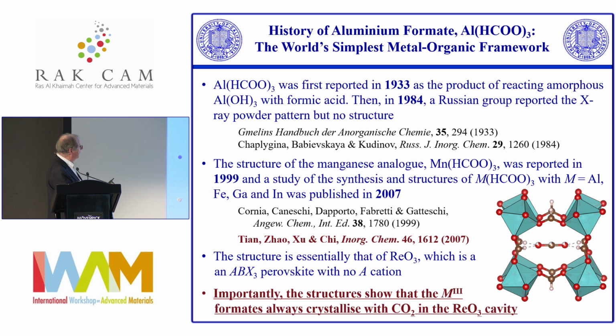And then nothing happened for about 50 years. And then a Russian group reported it. They reported an X-ray powder pattern, but no structure and no idea of the structure. And then some years later, in 1999, Gatteschi and his colleagues in Italy reported the manganese compound, this manganese formate. And they had a crystal structure. They showed that it's an antiferromagnet. It has a Jahn-Teller distortion because it's manganese 3 plus and so on. And then in 2007, which was just when we had started our other formate work, a Chinese group published a very interesting article, this Tian et al. in Inorganic Chemistry. And they made the aluminum, iron, gallium, and indium ones. And they reported all the crystal structures.